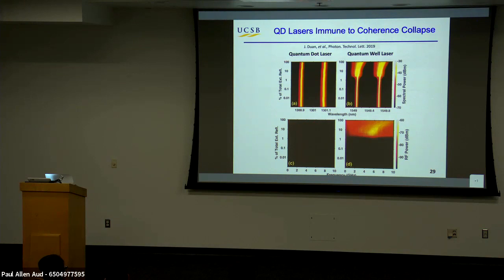So what this 100% is, light coming out of the facet is coupled into a fiber. 90% is sent to a reflector, and it's a 100% reflector sending back into the laser. And if you look at the high points up here, you can see these curves are curving a bit. That's because at this level, you're heating the laser. There's so much reflection back into the laser, it's heating up and shifting. You can see the same thing in the quantum well device as well. So, I mean, that's a big reflection, not a small reflection.